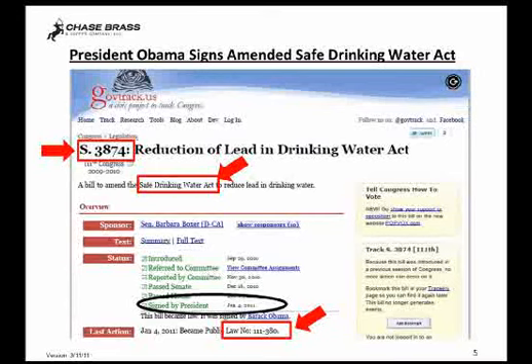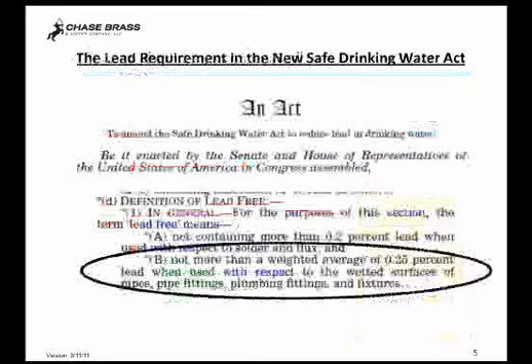It restricts the amount of lead, as we mentioned, to 0.25% weighted average maximum, and it goes into effect 3 years after the date of signing. So January 4th of 2014 will be the effective date for the national legislation, and that delay was requested in order to give companies time to transition all of the product that they were making for states besides California and Vermont to meet the requirements across all 50 states.